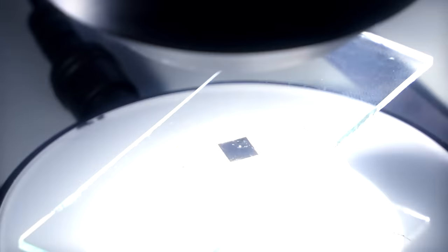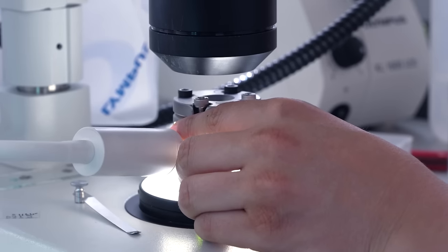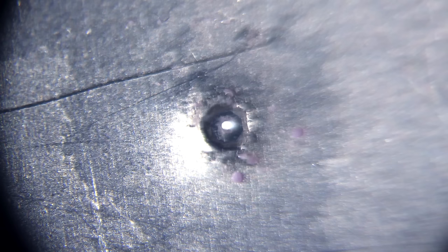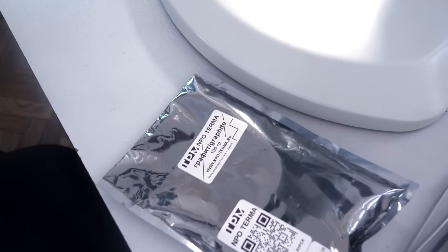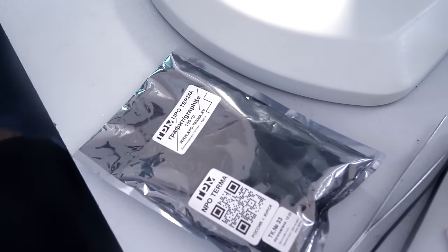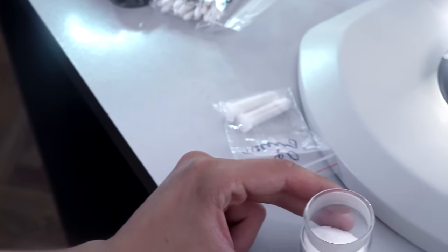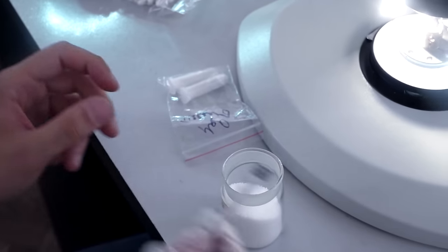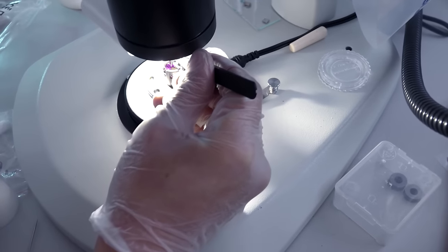To do this, we took another piece of iron foil with a hole in it, and compressed it between the diamonds one more time to create a high pressure chamber. After that, we decided to fill it with the initial substance for diamond production, namely graphite. But before, it needs to be lightly salted. Yes, that was not a joke. In order to evenly distribute the pressure in the chamber, you have to add ordinary table salt. It becomes softer at high pressure and fills the voids between the graphite particles.